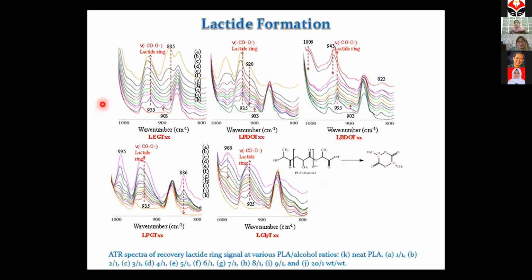Another surprising result we observed: in our objective, we just want to break down the polymer chain into smaller units. However, we also produce what we call lactide, which is a dimer of lactic acid. It has a ring structure like this from the reactions.